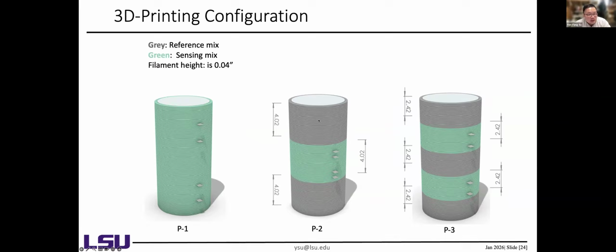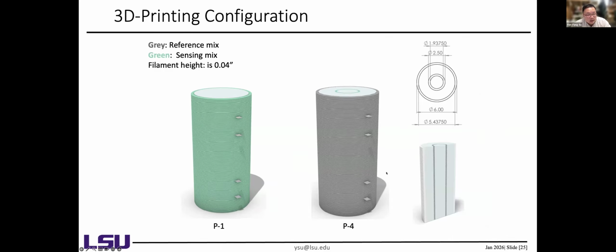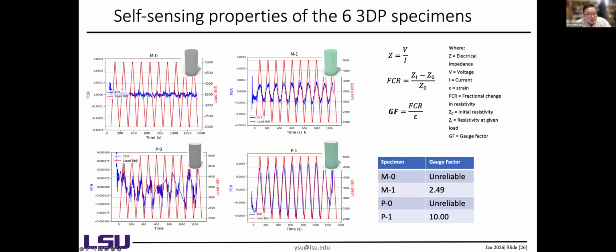And also we try different configurations, because as we say before, this special material is not cheap compared with a conventional concrete. We want to reduce the cost, so we end up designing a different mechanism, including this. We put only sensing mix in the middle of the structure, and we also have another set which is we split that in two separate sections. And furthermore, we also want to investigate if we just print a small core inside a structure, if that works as well. So this slide shows you the result.